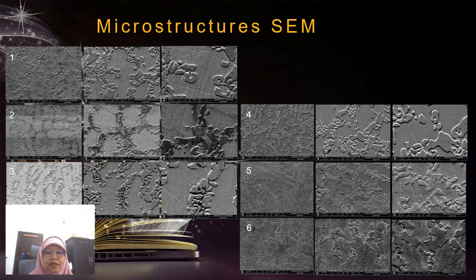This is the microstructure result. In my research, this figure shows the microstructure of FeAl-Mn alloy consisting of austenite, ferrite, and kappa structures, which are intermetallic compounds which surround the austenite grain. The dendritic pattern seems to dominate the microstructure of the FeAl-Mn alloy. After 1 hour of DCT process, no changes have been seen in the microstructure at all. Furthermore, in the 2-hour DCT process, the ferrite phase began to enlarge and the dendritic pattern began to change orientation, although it could not be said to be significant. The same thing happened to the 3, 4, and 5-hour DCT process.